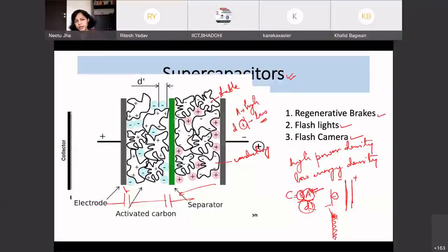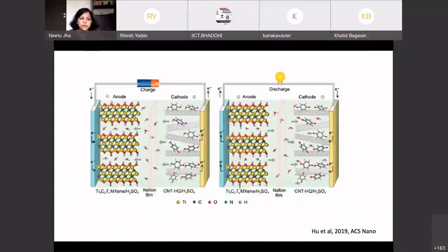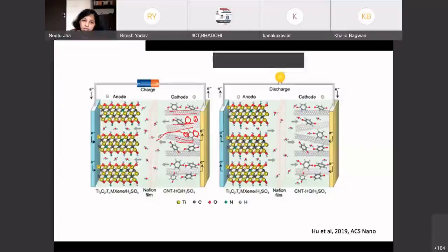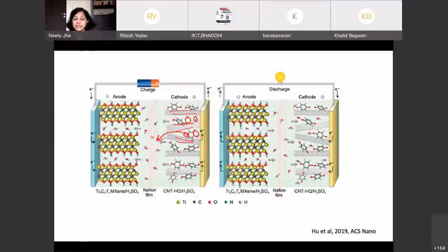Because the electrolyte ions which we are having here need to transfer and absorb somewhere in the pores. So the pore size should be optimum. And yeah, if we can design the electrode in such a way that the electrolyte ions can come and percolate inside the pores, and when you discharge it, it automatically goes back. So there is less diffusion limitation.